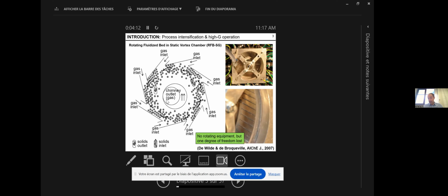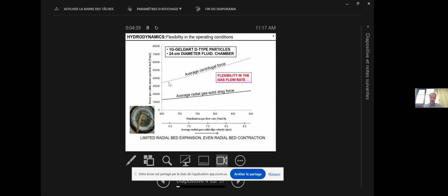And the fluid flows through the bed at very high velocities, while the particles are not entrained. So you have much higher velocities. The advantage of vortex chambers is that they are also very flexible in terms of the gas flow rate. When you increase the gas flow rate, you increase both forces, the drag force that goes inward, and the centrifugal force that goes outward. So you have a very high flexibility in terms of the gas flow rates. That is illustrated in this graph. You see here a bed of polymer particles. This is the gas flow rate, and you see that the drag force and the centrifugal force are both affected by the gas flow rate. And the bed is not lost when you increase the gas flow rate. On the contrary, it becomes even more dense.